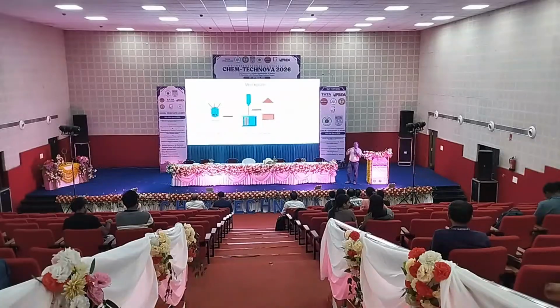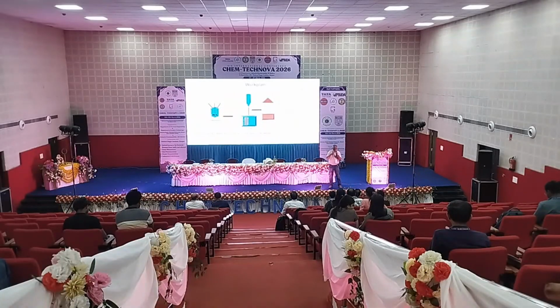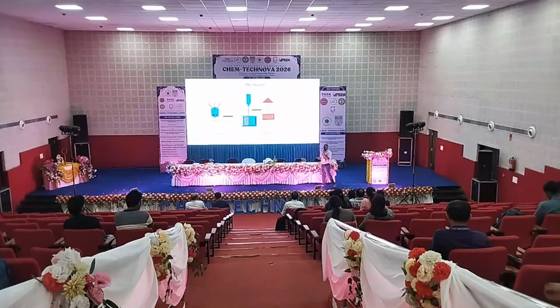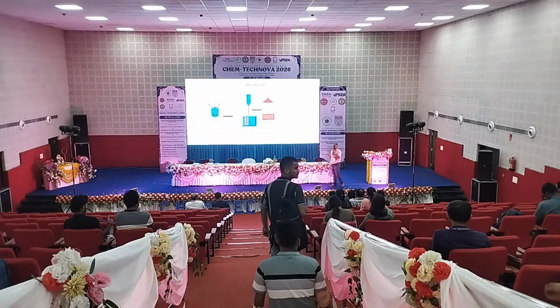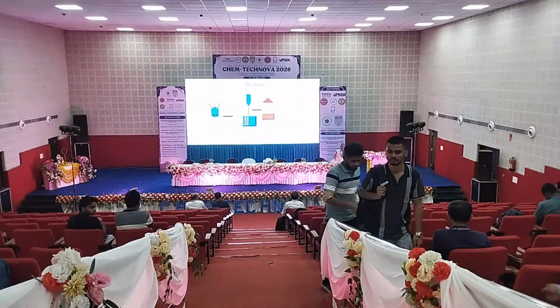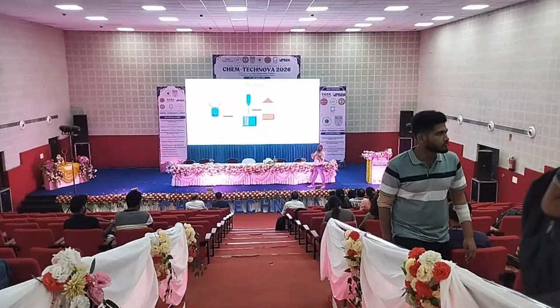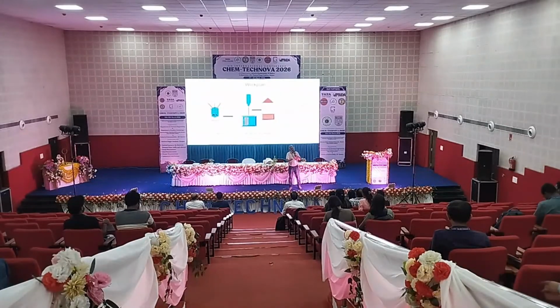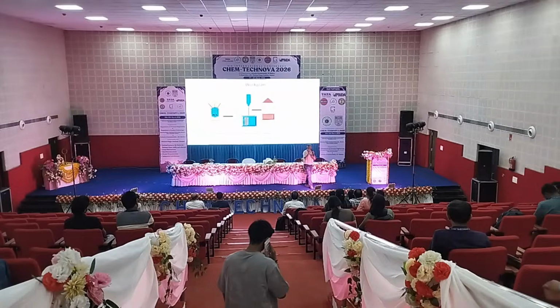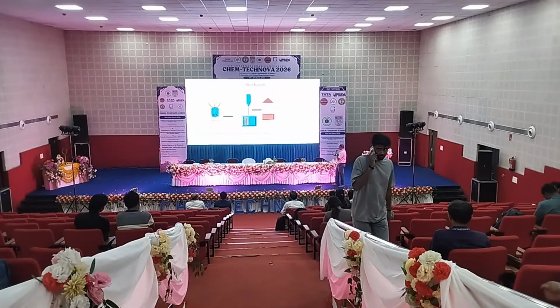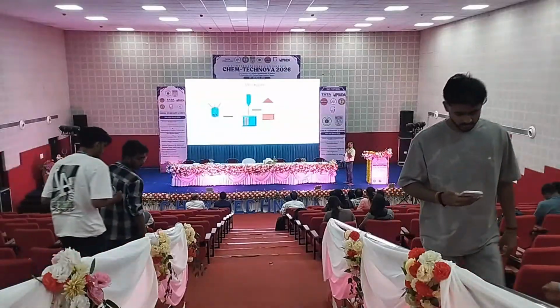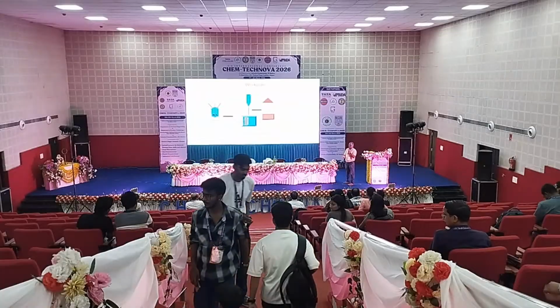So as I said, we used dual cure. That means we mixed two different resins, which can be light cured as well as temperature cured. Okay, so we used some kind of epoxy in the phenolic resin. Phenolic resin produces a lot of char. It is a very proven candidate for thermal insulation purposes, but we added epoxy because it acts as a glue for the metal nanoparticles. It is called an interpenetrating network. It will act as an interpenetrating network for the phenolic resin as well as the metal nanofillers or whatever particulate matter you are filling. So obviously you can use UV curing for the light curing part, or you can use a high temperature plate for curing the material.